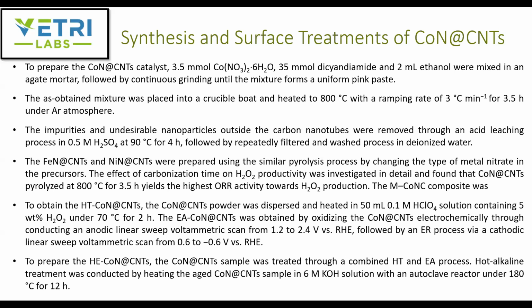And then, for comparison, they also prepared iron nitrogen doped carbon nanotubes and nickel nitrogen doped carbon nanotubes by a similar pyrolysis process, by just changing the metal precursor to iron nitrate or nickel nitrate. And the effect of carbonization temperature on the peroxide productivity was investigated in detail, and they found that the pyrolysis temperature needs to be 800 C. That would give the highest overall activity towards peroxide production.